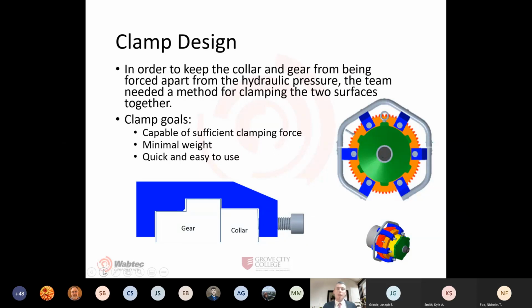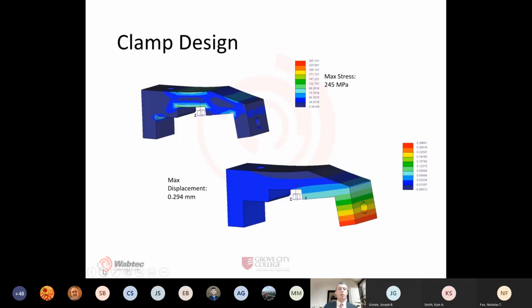The clamps are made from 4140 steel and are shaped to slide over both the gear and the collar easily, as seen in that bottom figure. An M18 screw closes the clearance and keeps the gear and the collar intact. We found that the hydraulic fluid exerts a total of approximately 58,520 pounds of separating force between the collar and the gear. Our use of 6 evenly distributed clamps results in about 9,700 pounds of clamp force each.